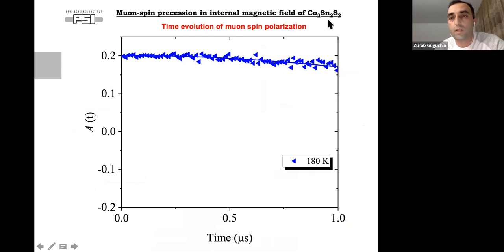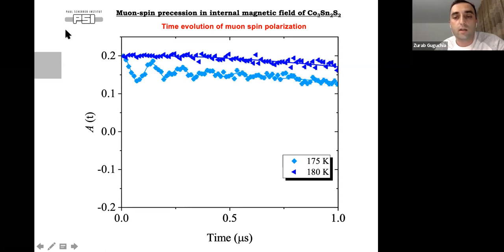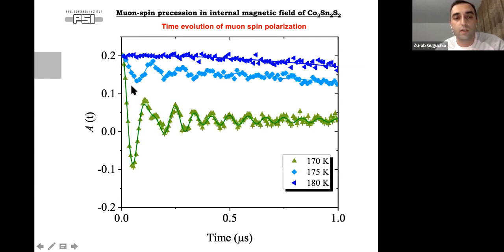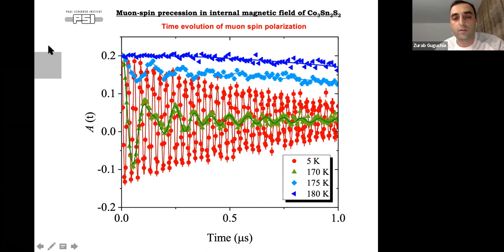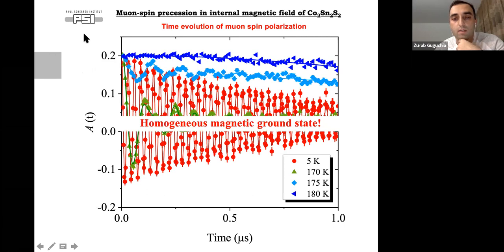So again, we started with the undoped compound. There's no indium so far. And now I show you the time evolution of the muon spin polarization. So this is a typical signal which you see in the paramagnetic state. It's 180 Kelvin. And then if you lower the temperature, you see already the appearance of the oscillations, which is the appearance of the long range ordering. And then we lower the temperature and we see again oscillations with bigger amplitudes, which means a large volume fraction. And finally, if I look at the signal at 5 Kelvin, you have a very low damping of the signal and a nice oscillation, which means that we have a homogeneous magnetic ground state in the system.